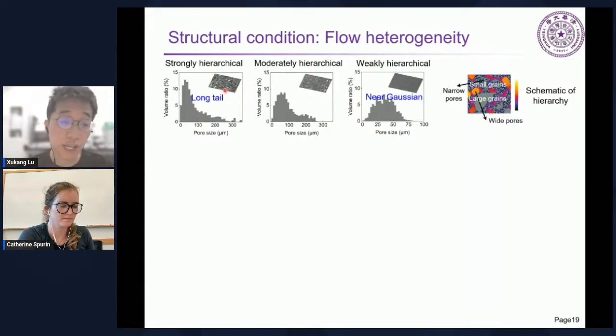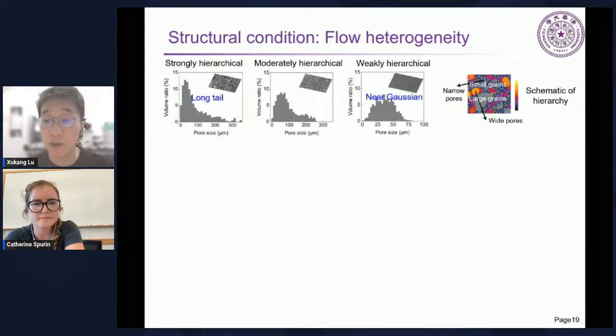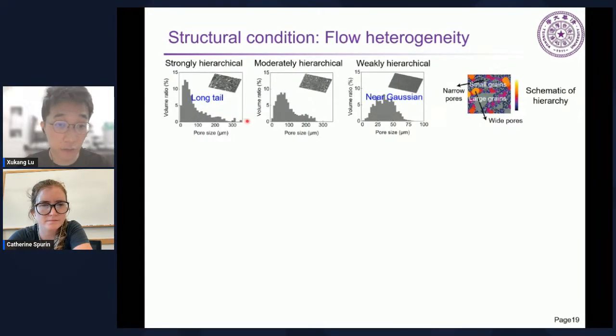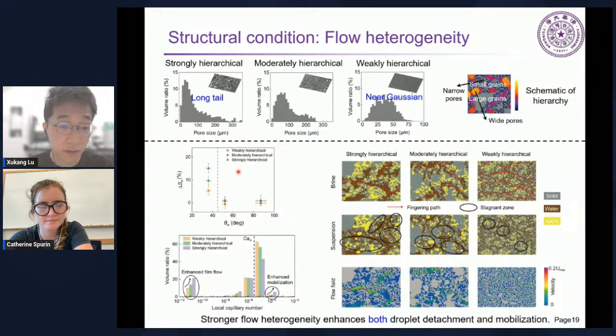So we changed the pore structure using a self-developed algorithm. Basically, we adjust the ratio of the small grains and the large grains during the structure generation. And that's why we call them hierarchical structure. Naturally, this hierarchy will lead to wide pore-size distribution and even this long tail feature, which is strongly heterogeneous. And we can flexibly adjust it to near Gaussian. And then we look at the performance in these different structures.